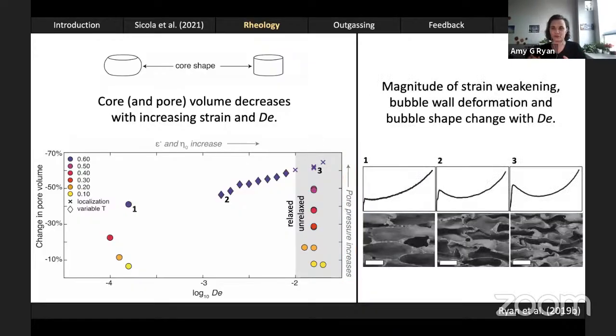A few other observations related to Deborah number are the magnitude of strain weakening, the bubble wall deformation style, and the bubble wall shape. So these columns here correspond to points 1, 2, and 3 in this figure, and I have representative mechanical data on the top row and representative microstructures on the bottom. What you can observe is there's more strain weakening as the Deborah number increases. And we go from bubble shapes that are sort of squashed spheres to these really strange contorted shapes. Likewise, the bubble walls themselves go from something sort of planar and flat to really bent, buckled, and folded.